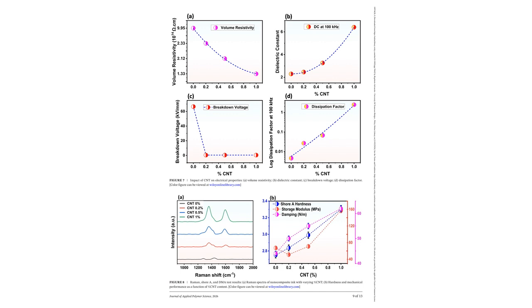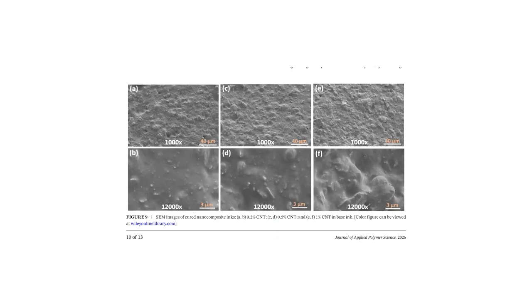added. This suggests that at higher concentrations, the CNTs begin to form a continuous percolated network throughout the polymer matrix, which dramatically reinforces the material. The damping force also nearly doubled with 1% CNT loading, indicating a much greater ability to absorb and dissipate mechanical energy. To get a visual confirmation of the material's internal structure, the team used a scanning electron microscope, or SEM.